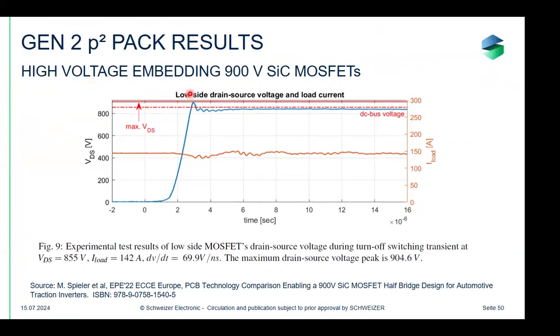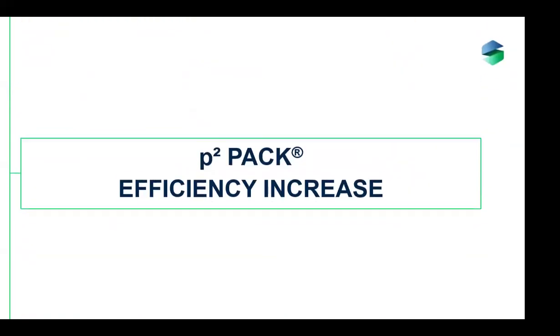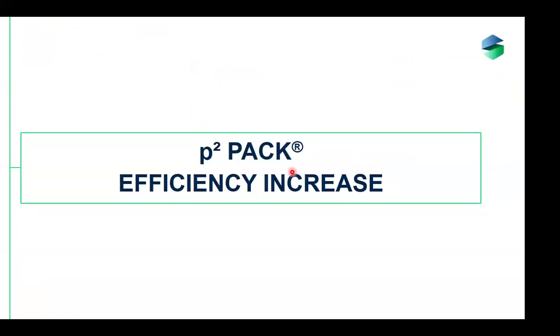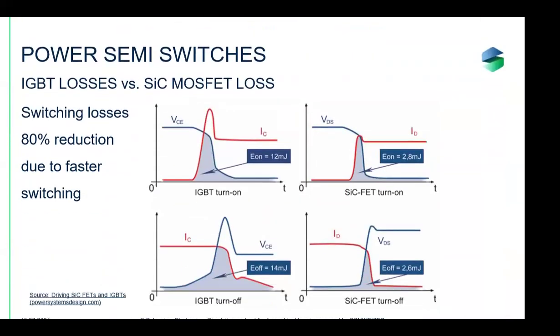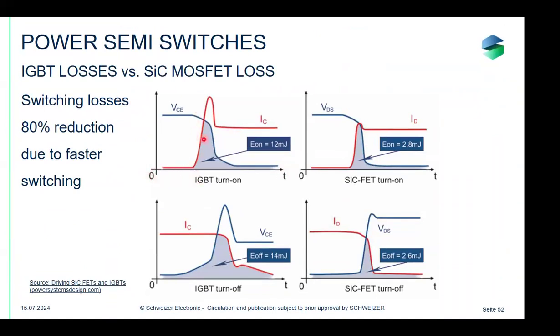Here you can see the switching behavior with a very fast switching of 70 volts per nanosecond. And as you can see, the overshoot is very little, and also the ringing is very, very short in time. So as I told you, if you are interested in that, I can give you the publication. And interesting was that for the double pulse testing, double the nominal current was used. So it was very fast, very high current, and very low overshoot voltage. So why is this important? If you can switch fast, you can increase your efficiency, because you spend a shorter time in these intermediate states.